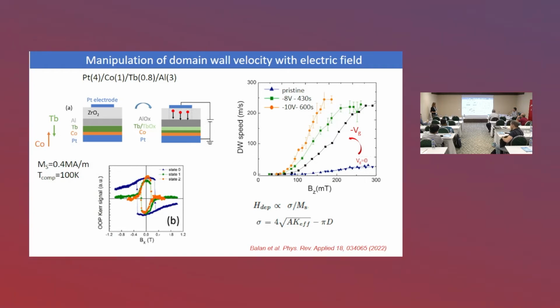So before applying the gating, you see that the domain wall velocity, this time driven by field, is very, very low. Even with 300 millitesla, we have 20 meters per second. How do we explain this very small speed? We explain it by saying that you have a very strong depinning field. The depinning field depends on the domain wall energy divided by the magnetization. The domain wall energy is large because of the large anisotropy, and the magnetization is small because we have a ferrimagnet, so we have this very small increase of the velocity.